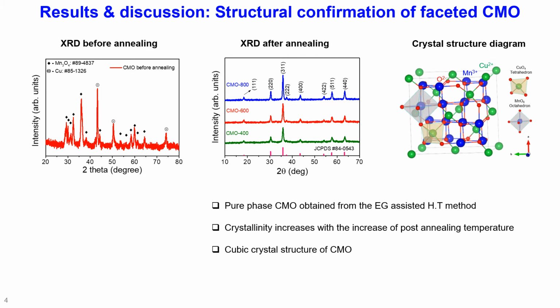Results and discussion. Structural confirmation of faceted CMO. Here I have shown the XRD before and after annealing. Before annealing, we could clearly see the formation of a mixture of copper and Mn3O4, and then after annealing, these two undergo the solid state reaction to produce CMO. Here we can see that the pure phase CMO has been obtained from our EG assisted HT method, and the crystallinity of the CMO increases with the increase of post annealing temperature, 400, 600 and 800 degrees Celsius. The cubic crystal structure of the CMO has been obtained from this method, which is shown in the crystal structure diagram.